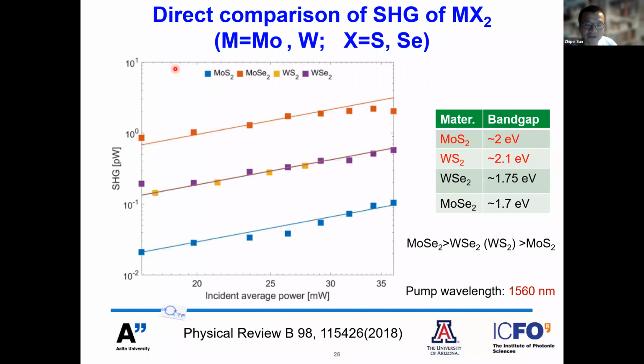But the results we got are completely different from what we estimated before the measurements. Here you can see that with MoSe2, we get a much stronger nonlinear response. With WS2 and also WSe2, we get a pretty comparable nonlinear response. Surprisingly, with MoS2, we get a very low conversion efficiency.